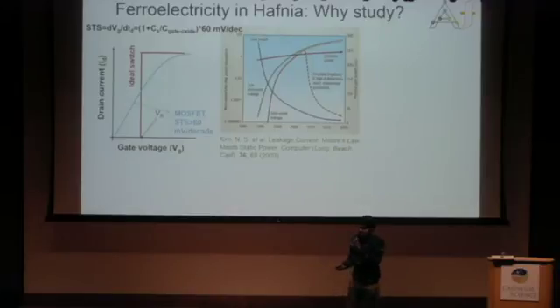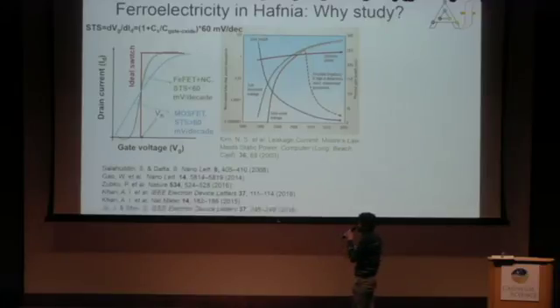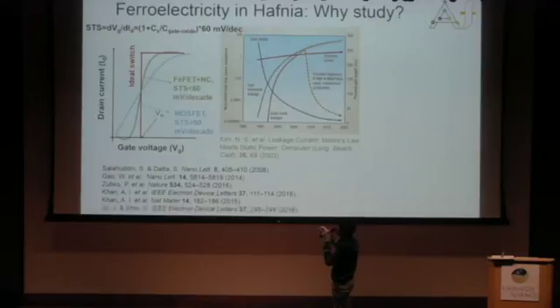So this is bad, but fortunately we have a solution for that, which is to try to make this quantity negative: use a negative capacitance as a gate oxide, and it's well known. So instead of a MOSFET, we'll be using a ferroelectric FET or a negative capacitance FET, and negative capacitance has been demonstrated in these ferroelectric materials by several groups in the recent past.